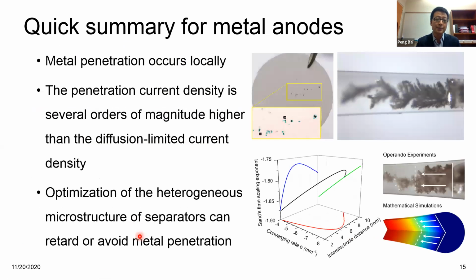So as a quick summary of this part, I hope you now realize that metal penetration occurs locally, as we already showed. And when penetration starts to happen, before you have the eventual short circuiting, the penetration current density for that local region is several orders of magnitude higher than the diffusion-limited current density designed by existing models, because they handle the homogeneous situation. Then, to optimize the heterogeneous microstructure of the separator, if we can promote the lateral transport, we may eventually retard or even avoid completely the metal penetration.